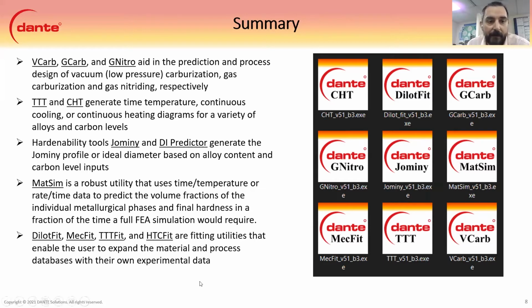And then, like I said earlier, for fitting utilities, you'd fit your experimental data to the DANTE database. We have DilotFit, which is used for dilatometry data, MecFit, which is used to fit the mechanical properties of the individual phases, and then TTT fit and HTC fit are utilities that help us fit TTT diagrams to DANTE. HTC fit is kind of unique. It needs to use Abaqus right now, and it's used to fit heat transfer coefficients based on thermocouple data.